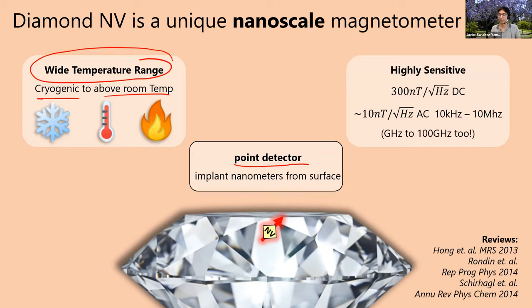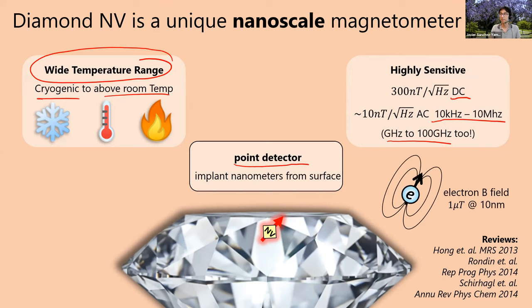It can measure really small magnetic fields at both DC and AC frequencies, going up to gigahertz and many gigahertz in frequency. So it's highly sensitive and also relatively high bandwidth as far as a magnetic sensor is concerned. As a reference, it has no problem measuring a single electronic spin if it is placed about 10 nanometers away.